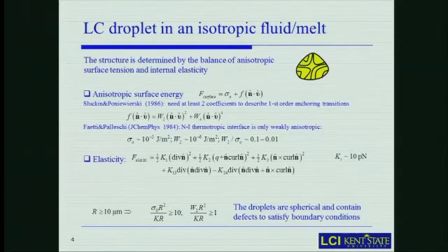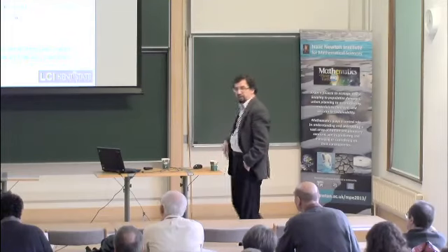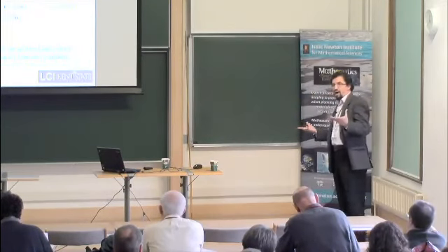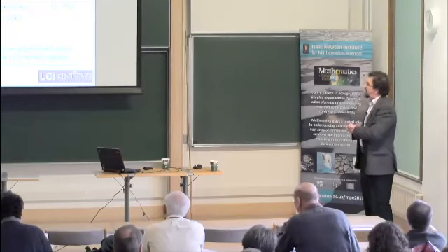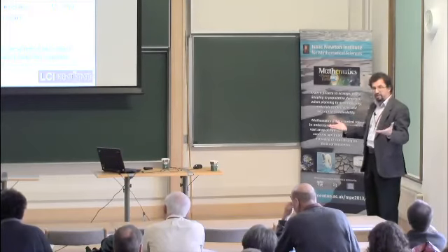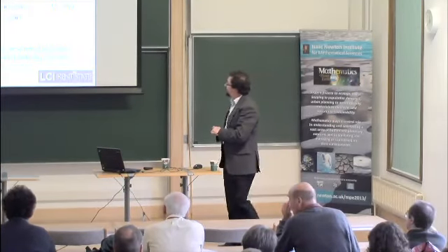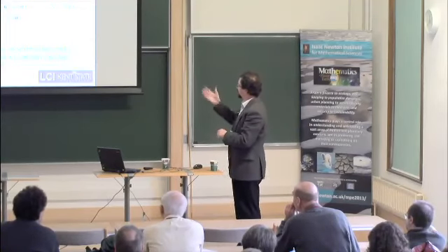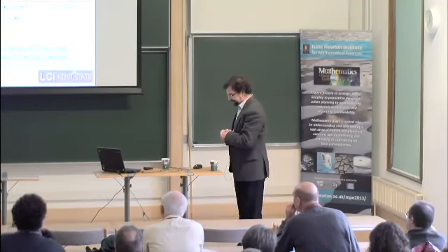Now the elasticity, we can use the Landau-de Gennes approach, the Q-tensor formalism, and we can also use the Frank expression written here that contains the three bulk terms and three surface-like terms, and I think there will be talks about these things. I would like just to mention that in many problems, people just restrict their attention to these three bulk terms. K24 becomes important when the topology of the volume changes, or when you introduce topological defects. Blue phases are a good example of this situation. But in most of our examples, we are not dealing with surface-like terms in this presentation.